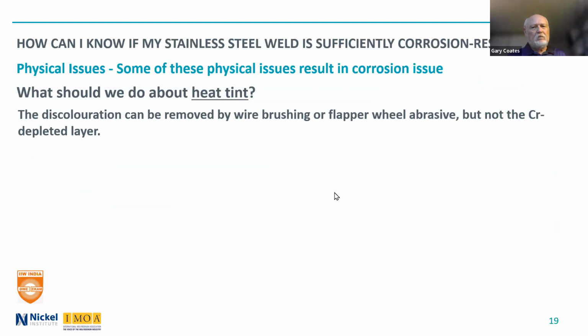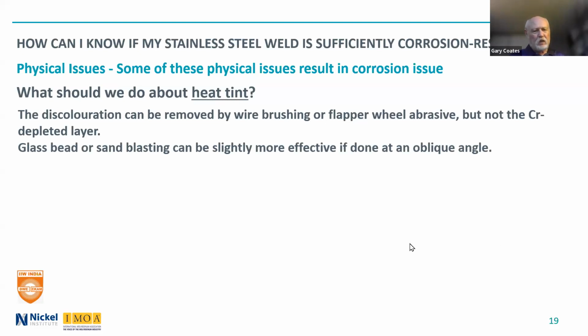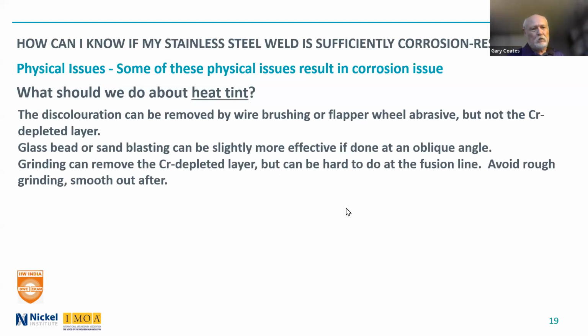So what should we do? Well, about heat tint, you can actually remove the discoloration by wire brushing or a flapper wheel abrasive, but not necessarily the chromium depleted layer. A lot of people will glass bead or sandblast with a proper silica sand. It's more effective if done properly, not always easy to do around welds because you have a rough surface there. Grinding will remove the chromium depleted layer, but it's hard to do at the fusion line unless you flatten out the entire weld bead itself on the exterior. And of course, if you use a rough grinding wheel to start with, you want to smooth it afterwards, because the higher the surface roughness, the more likely it will pit also.